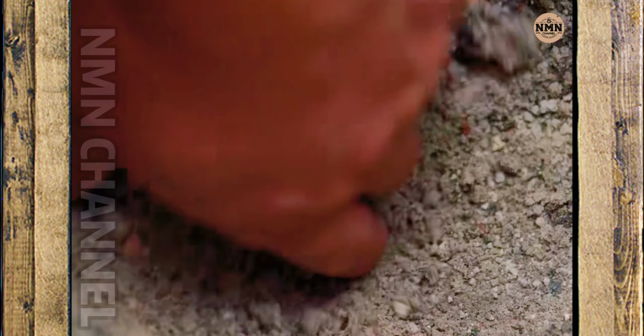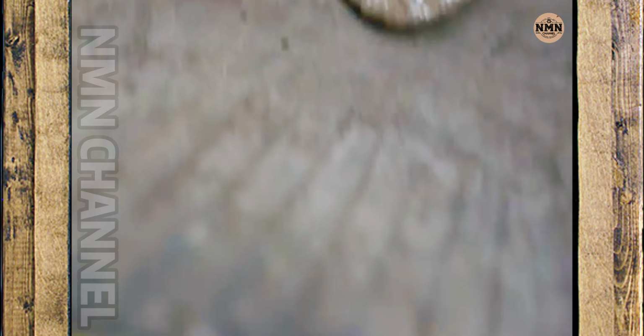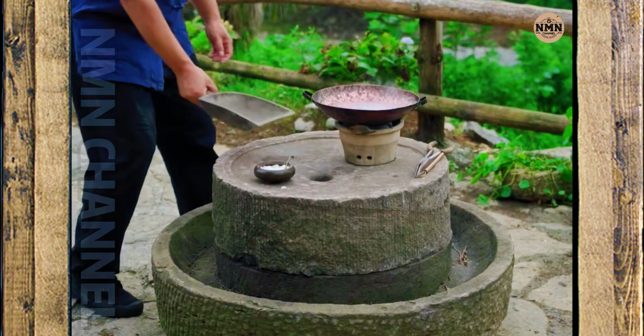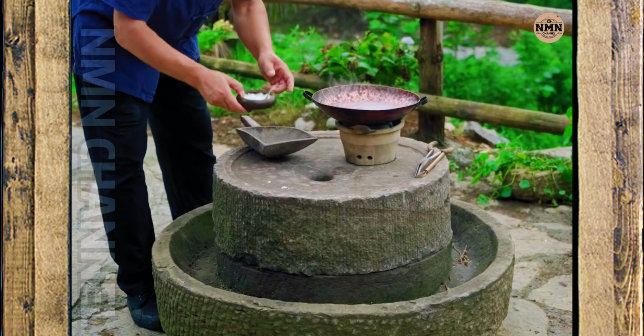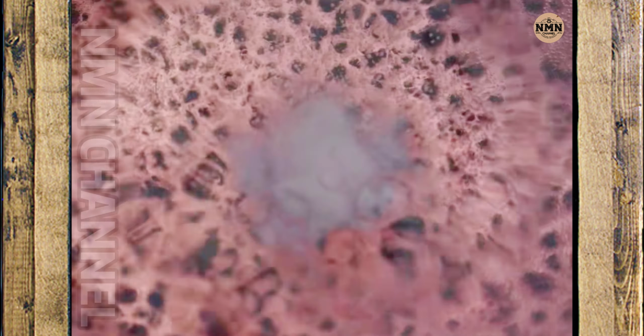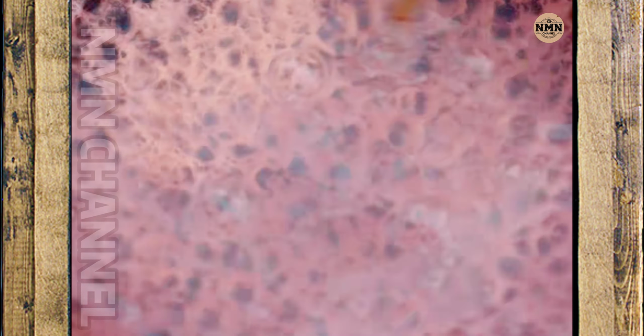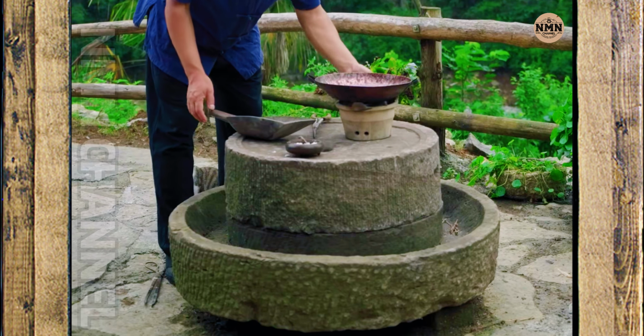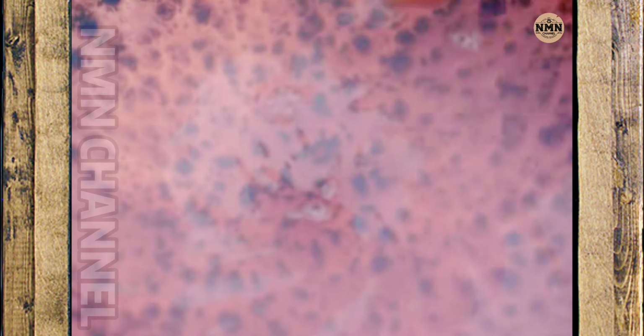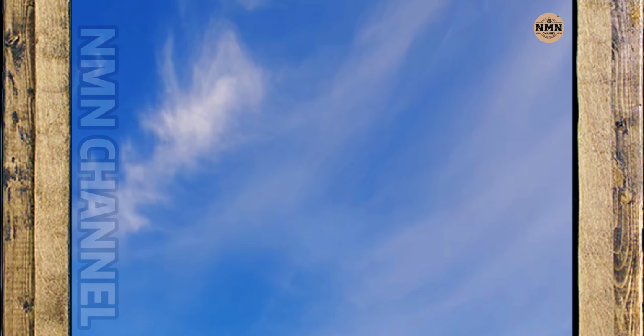After several firings, the silver was finally revealed, but not quite pure. Impurities still clung to the surface, like a layer of undissolved luster. A basin of clear water was mixed with alum, colorless, odorless, but a solution capable of washing away the last layer of impurities on the silver's surface. The silver was dropped in and lay quietly, and like a mirror that had just been polished, the light of the precious metal gradually became clear.